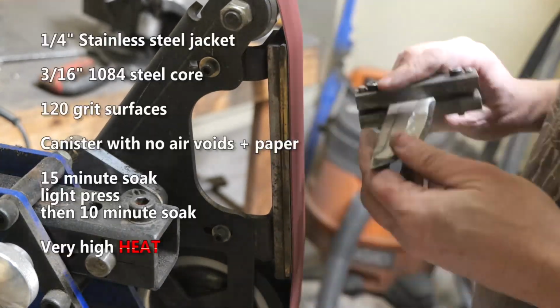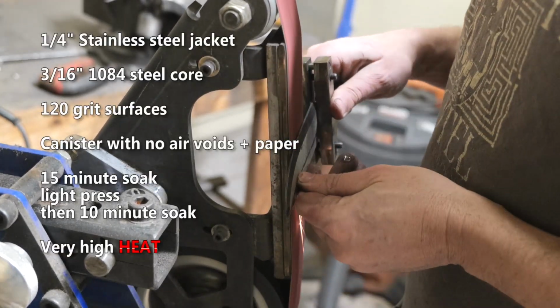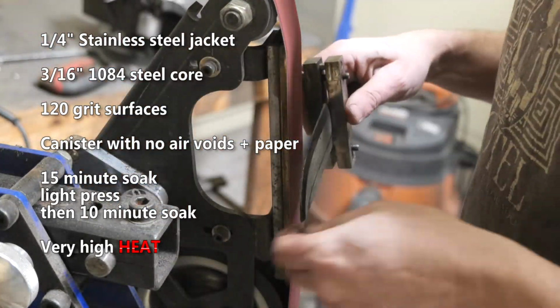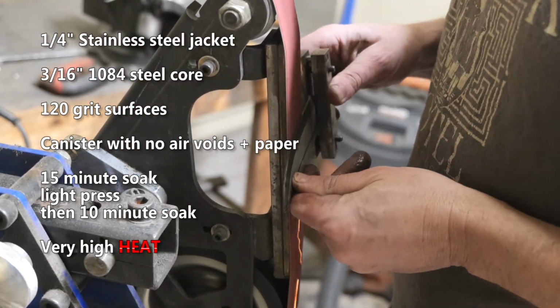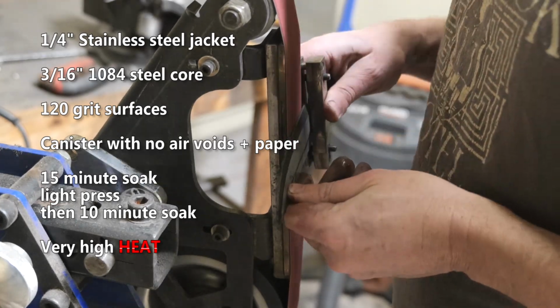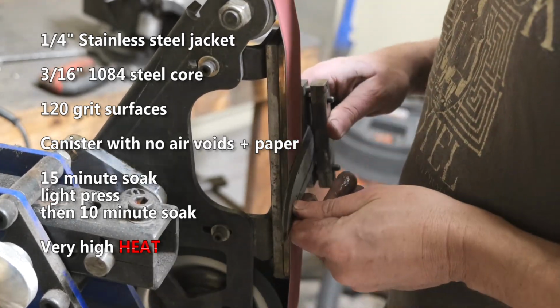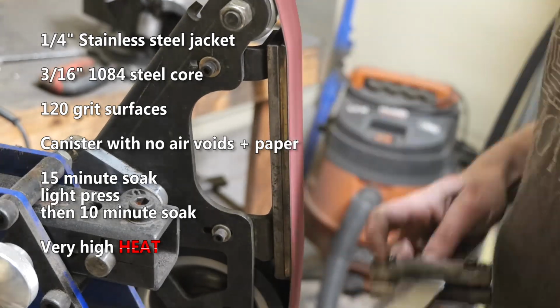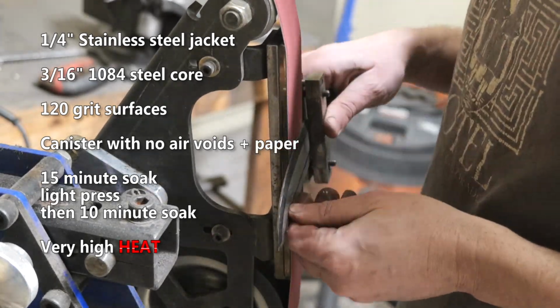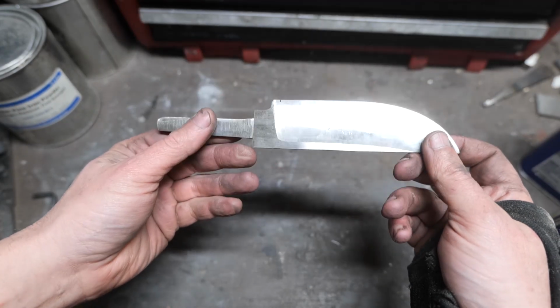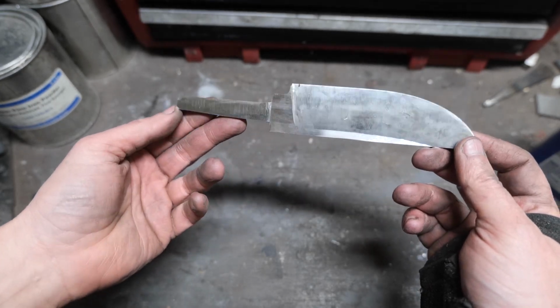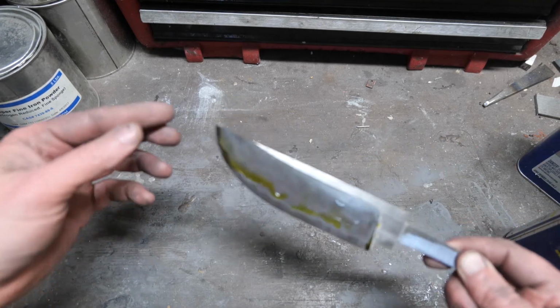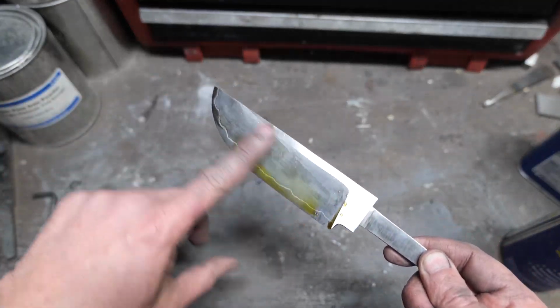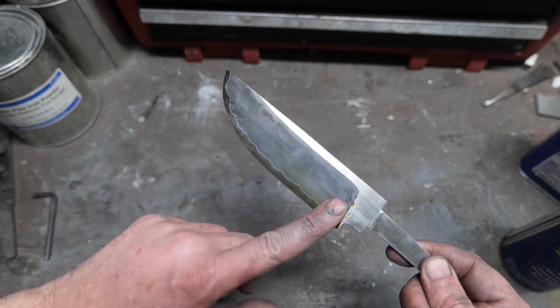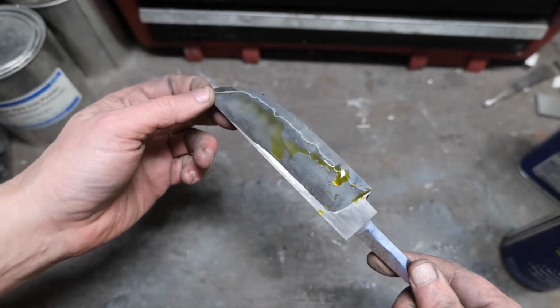So to recap, we started with 1/4 inch stainless steel and a 3/16 inch 1084 core. We didn't use nickel sheets, though we probably could have. An oxygen-free environment, long, super high temperature soaks, like close to melting steel temperatures, got the job done with some really solid welds. So at any rate, maybe this will help you with y'all's venture into stainless sanmai. And maybe not. You probably could teach me something. But I do like that transition line. Look at that, guys. That is going to be nice.